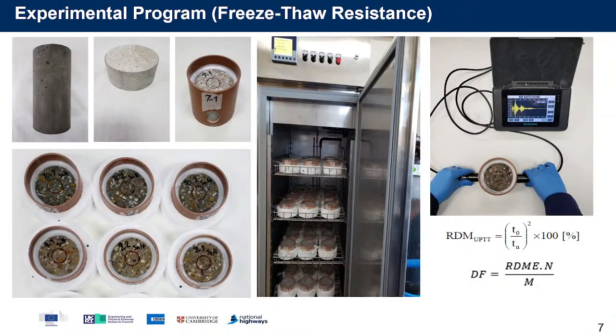This slide shows the freeze-thaw test method that has been adopted in this study according to the BSI standard. You can see the sample preparation, where I have used concrete discs with dimensions of 100 by 50 millimeters. I put the samples in plastic tubes, which are insulated with polyester, and then in the freezing chamber. They are subjected to temperature reductions from 20 degrees Celsius to -19, and then returning back to 20 degrees Celsius. For freeze-thaw resistance without de-icing salts, I used 3 millimeters of deionized water on top of the specimens, and I used ultrasonic pulse transmission time to measure the relative dynamic modulus of elasticity.